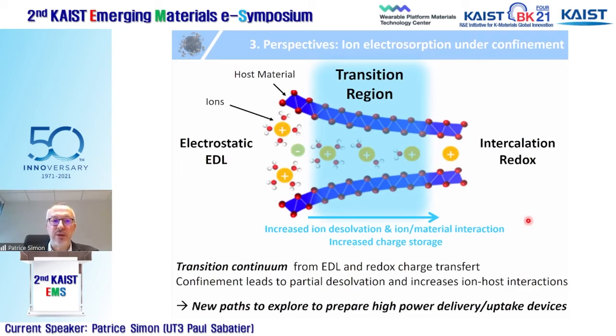This is a continuum region between double layer and redox, where the confinement of the ions leads to partial desolvation and results in an increase of ion-host interactions and capacity enhancement versus conventional double layer adsorption, but still with super high kinetics. So this shows that there are new paths to explore to prepare high power delivery or high power uptake batteries that can be charged within a few tens of seconds. And this is really what MXene materials can do now. Research effort has to be directed toward this new path to explore. So this is the end of my talk.